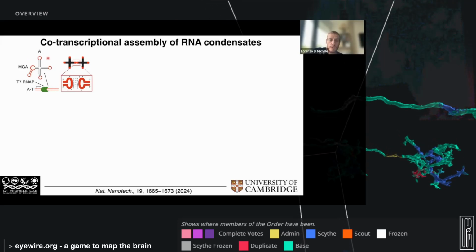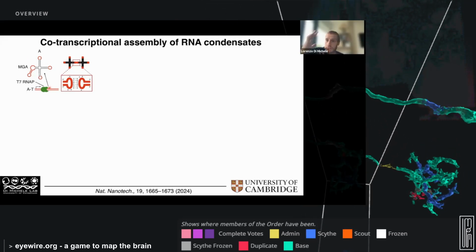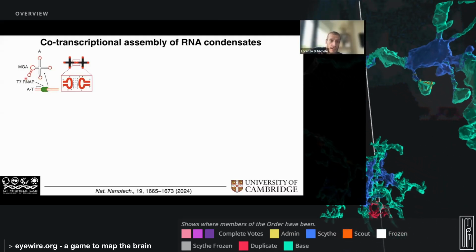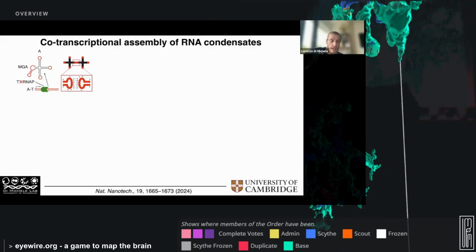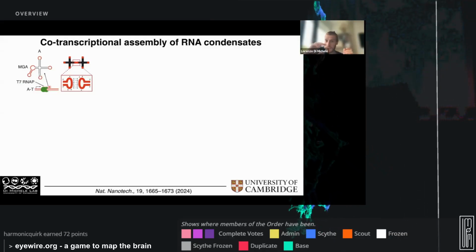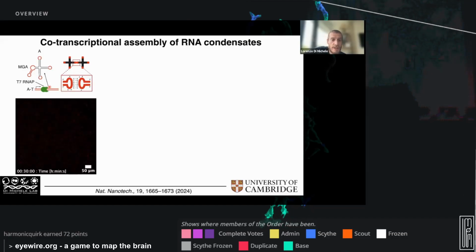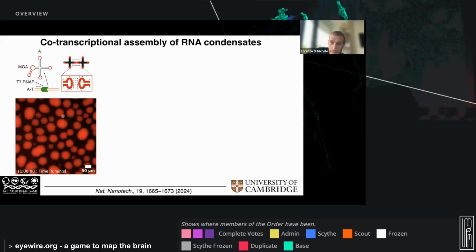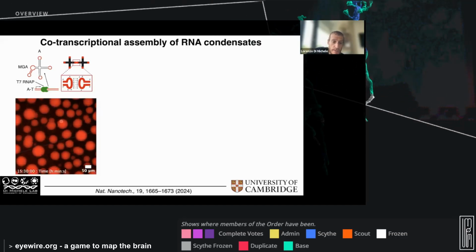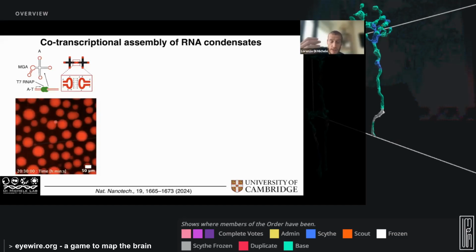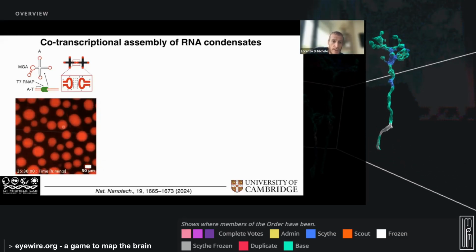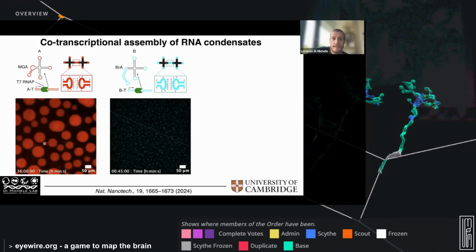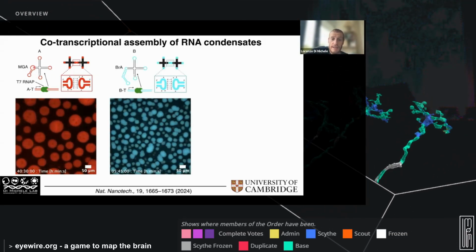Then all that you need to do is to encode this in a certain bit of DNA, which can be linear or circular, under a T7 RNA polymerase promoter. In this case, we're going to do an in vitro transcription reaction. You form loads of this RNA, and you see that eventually you get nucleation of big droplets, coalescence, they grow, they are quite large, larger than a cell. Eventually, they will start degrading, so they form condensates. So this we call the A design.